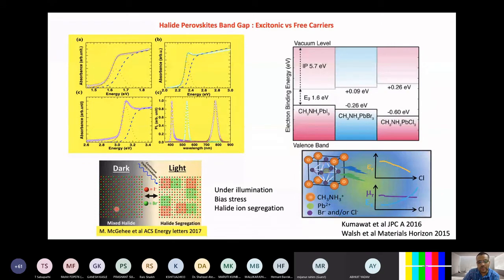So the band gap tuning which was demonstrated is all transient. It's there as long as the temperature is not high, as long as not enough intensity is being provided. If you are making a solar cell with a tunable band gap, pure with single MA, it's a problem. Now people have demonstrated that by replacing the CH3NH3 with FA and mixed cations, they could maintain the band gap stable without seeing halide ion segregation.